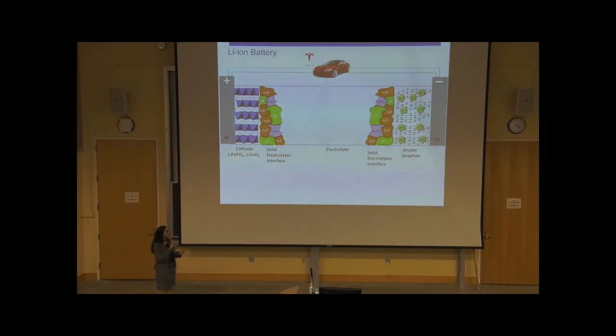Like any other battery, it contains a positive and a negative electrode, where the positive electrode is generally a very pure lithium metal oxide, and the negative electrode is typically graphite, a layered form of carbon. When we discharge the battery, that's when we take energy from the battery, these lithium ions start migrating from the anode side, traveling through the electrolyte, and they intercalate into the cathode, and then electrons complete the outer circuit. The reverse process takes place when we charge the battery. So these lithium ions travel through the electrolyte and move back to the graphite anode when we charge this battery.